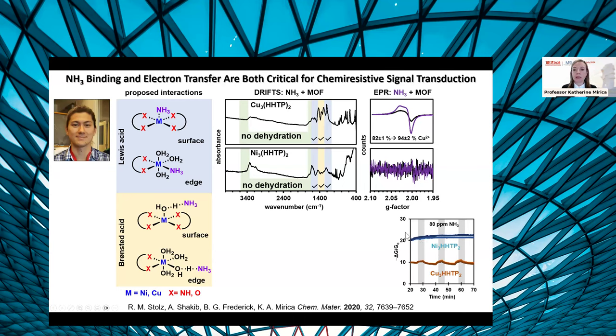So for the nickel-based material, it's not that there's no binding, but upon that binding, there isn't a significant redox shift or perturbations to the electronic properties of the material that, in contrast, for the copper material are observed very strongly. So basically, our picture is beginning to emerge where upon binding of ammonia to the surface of the framework, some of the materials are able to transduce that binding event through changes in the redox states of the constituents of the framework, while others do not.